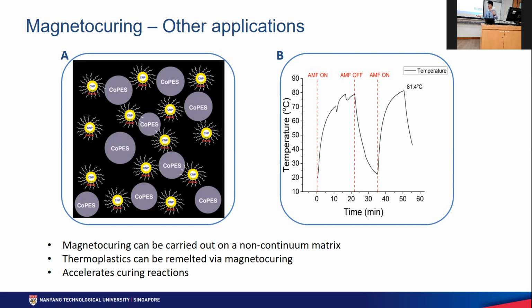So thermoplastics often come in the form of granules or small pellets. When I mix that with these functionalized nanoparticles, they actually work. So I found out that magneto curing can be carried out on a non-continuum matrix. At room temperature, thermoplastic will recrystallize, but these thermoplastics can be remelted with the addition of nanoparticles. You can look at it on the right over here.